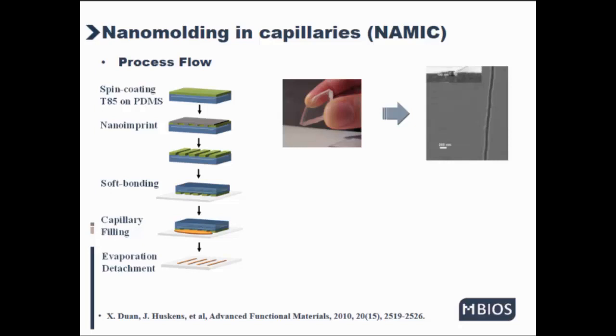polymer films. And after that, the PDMS mold was placed in contact with the substrate so that the nanogrooves form nanochannels. After the formation of the nanochannels, a drop of PEDOT:PSS was placed at one end of the nanochannels. So the liquid fills the nanochannels by capillary action. After the solvent completely evaporated, the PDMS mold was gently removed from the substrate, leaving the nanowires on the substrate.